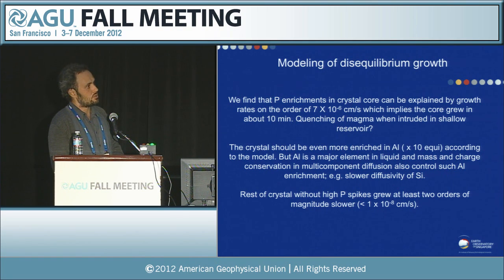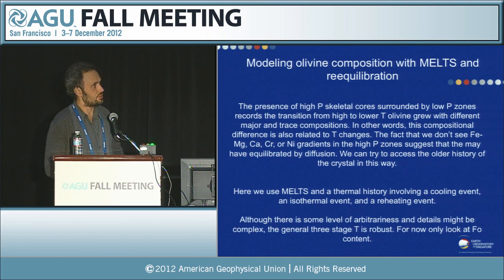As I said, the high aluminum should be more enriched, but aluminum is a major element. So if you want to multiply your aluminum content in the melt by 2, from whatever, 15 to 30, there's no way this is going to happen. Particularly because you have to conserve mass and charge, so you have to start thinking about multi-component diffusion. Basically, the aluminum will not enrich so much if silicon doesn't allow it to do it. So I would say this shows the model is for trace elements, not for major elements. So that's okay that we don't see the enrichment in aluminum. And as I said, the rest of the crystal grew at much slower rates.